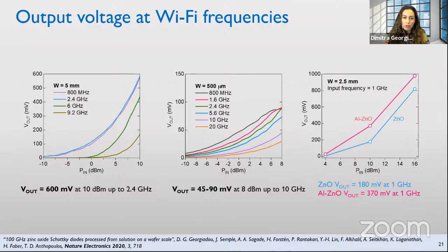And again, a comparison of the aluminum doped with the undoped zinc oxide shows that the aluminum doped is beneficial, as at 1 gigahertz, the output voltage is almost doubled in the aluminum doped zinc oxide.